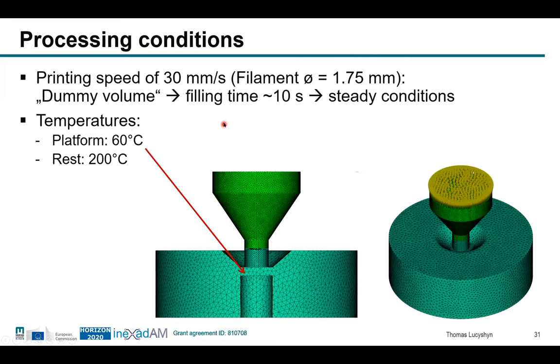Injection molding is a non-continuous process. So as soon as the cavity is filled, the simulation stops. But we wanted to simulate some kind of continuous flow through the nozzle. So what we had to do is to create some dummy volume around this area where the melt could flow in without any flow resistance. So it's a huge volume. There is no small gap. So the material can go easily in here without any flow resistance.